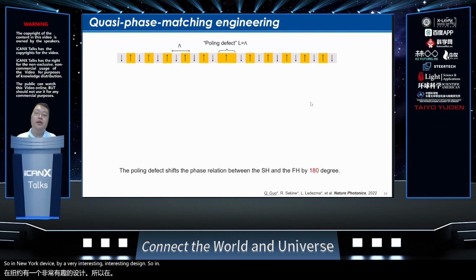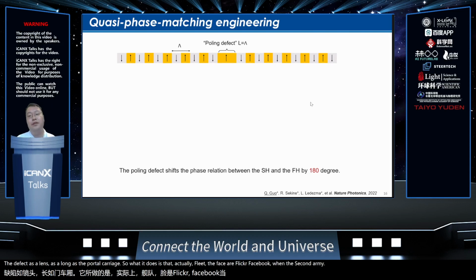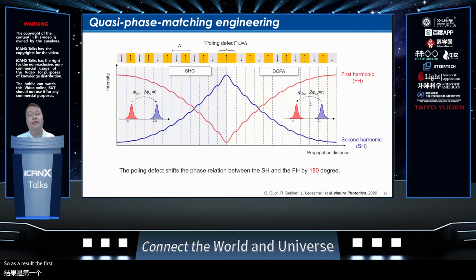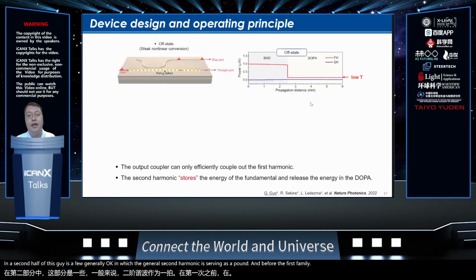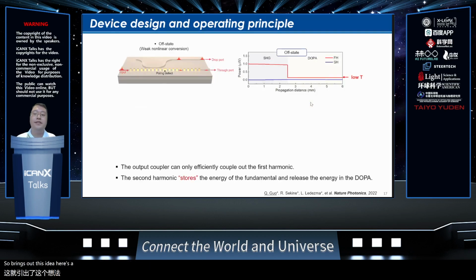So in the middle of the waveguide, we have a longer ferroelectric domain called a poling defect, and the defect has a length as long as the poling period. So what it does is that it flips the phase between the second harmonic and the fundamental by 180 degrees. So as a result, the first half of the waveguide is the second harmonic generation, and the second half of the waveguide is a degenerate OPA, in which the generated second harmonic is serving as a pump to amplify the first harmonic. So based on this idea, here's the design of our optical switch.